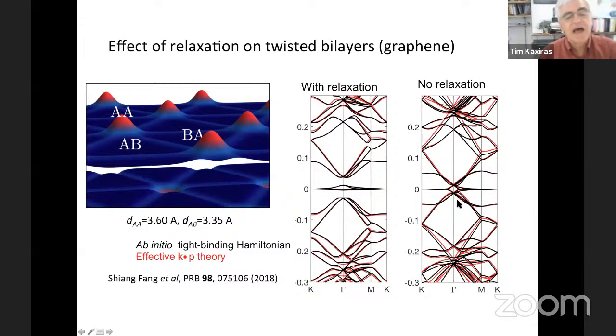If you don't allow the atoms to relax at all, and you just put one layer on top of each other, you see clearly this is wrong. This has nothing to do with experimental observations, as I mentioned earlier, with mini gaps and with the gaps and flat bands and so on.